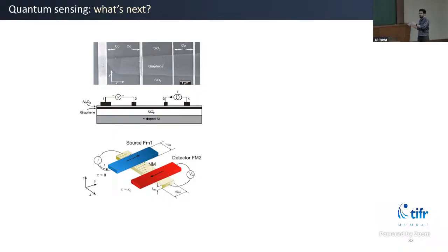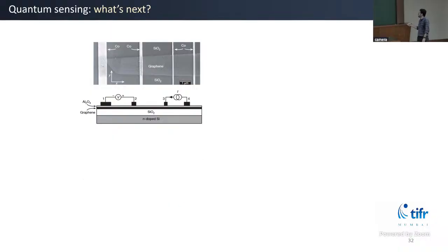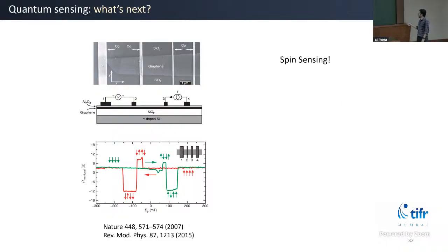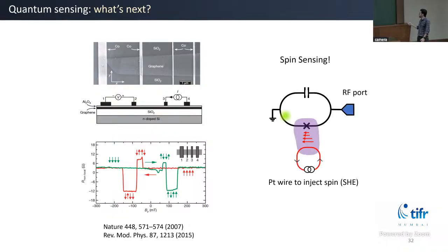So you can inject a magnetic excitation into this graphene flake, and it acts as a bus and goes to your junction for sensing. This is a direction we would like to explore, where our device will work as a spin sensor. We have an LC resonator, a non-linear resonator, and on the graphene flake you can use some ferromagnet to inject spin and then detect that using a Josephson junction. Our estimation is that this device will be much more sensitive than these devices, because those are literally DC devices where you send a large current to get a measurable voltage, whereas our device is a non-linear resonator, and what you see is the resonance frequency shift.